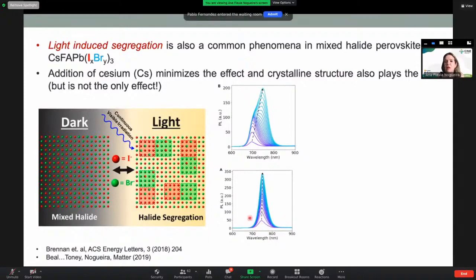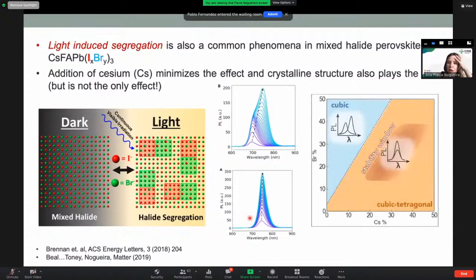Also, in this study we show that it depends on the crystalline structure, again in terms of stability. For instance, we observe that most of the cubic perovskites with these different ratios between iodide and bromide are unstable. But by increasing the cesium concentration, I can go to more tetragonal structures, and then we gain in terms of stability. So that's the reason the crystalline structure of the perovskite is really important.